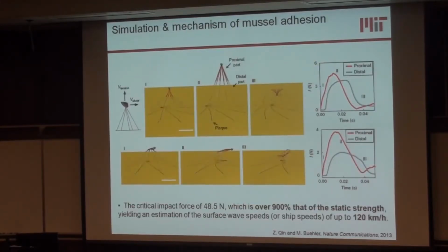And then in our simulation, we give initial velocities to those mussels to mimic the impact on them, and we study how the force distributes inside the network. It seems that for the stiff material, the loading becomes higher than for the softer material. So it means the softer material is able to damp out the impact force once the force is transduced from the mussel to those mussel threads.